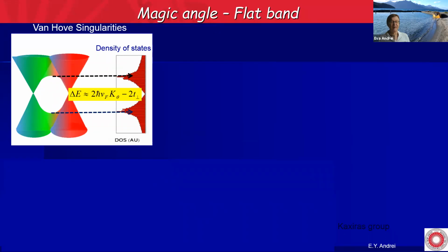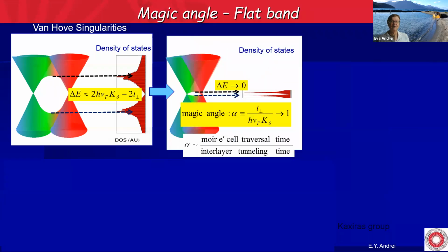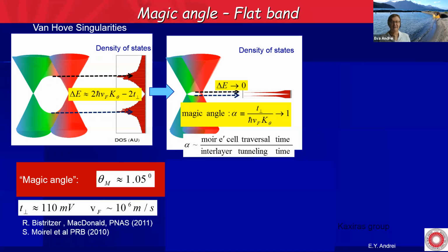Now notice that when I decrease the twist angle, these Van Hove singularities or the saddle points are going to come closer and closer to each other. And there is finally a twist angle, which was dubbed the magic angle, where this gap goes to 0. It roughly happens when the Moiré cell traversal time is equal to the interlayer tunneling time. And that's when you get a flat band.